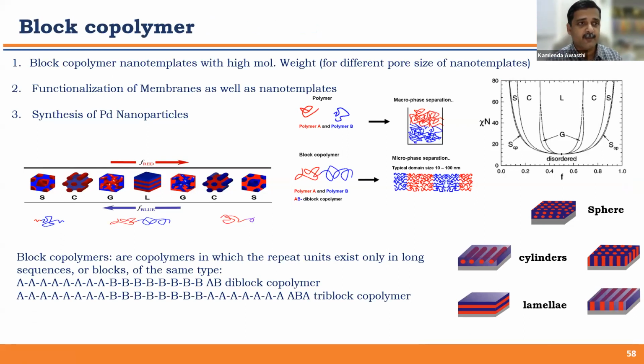Okay, so in the next 5 to 10 minutes, I will just discuss another polymer, the block copolymer. This is different from normal polymers, like if we mix polymer A and polymer B. When they go through macrophase separation, the polymers mix randomly like this. But when we use a block copolymer, like polymer A and B, they come in a particular pattern like AB, BA, AB, and so on. These are the various fractions of the blocks, meaning A and B. Here you can see sphere, cylinder, lamella, and so many morphologies that we can make by making different variations. By changing the red polymer, you can see how the morphology is changing, and by changing the blue part, you can see how the morphology is changing.